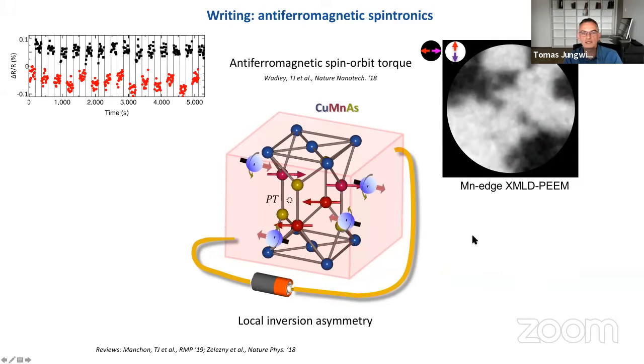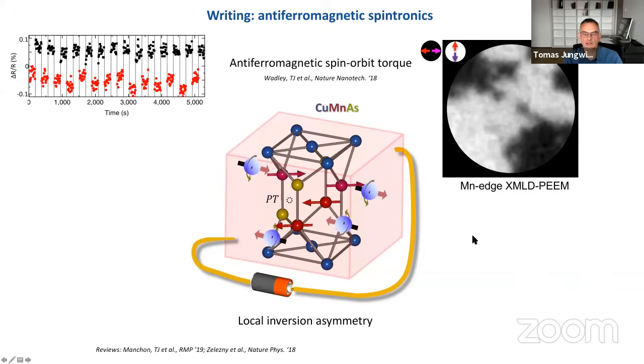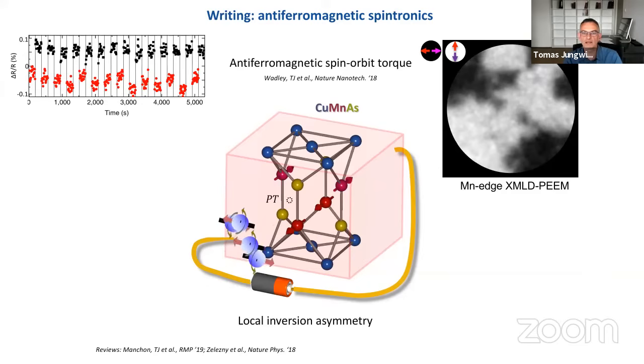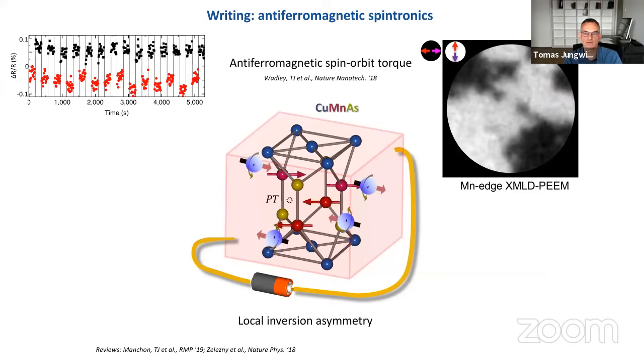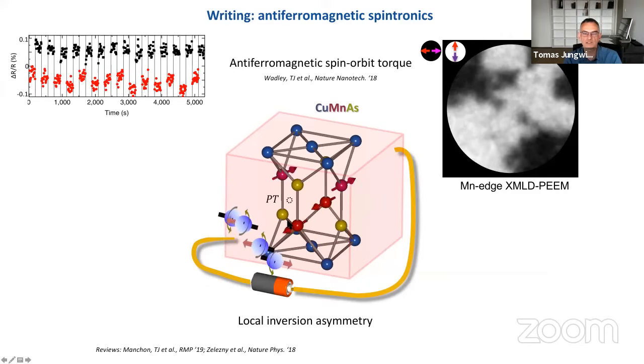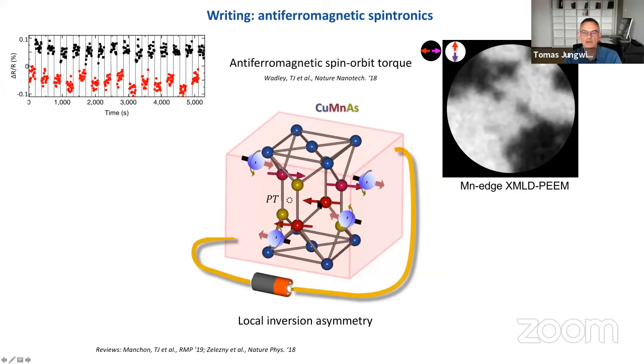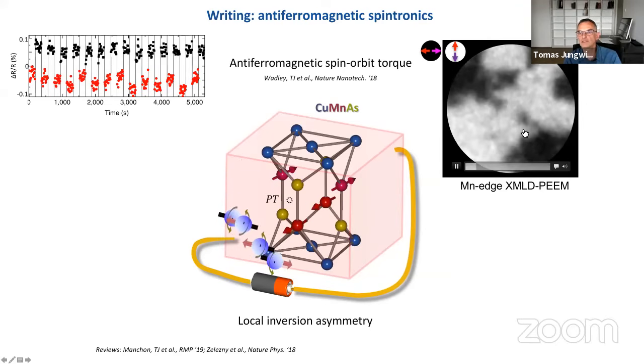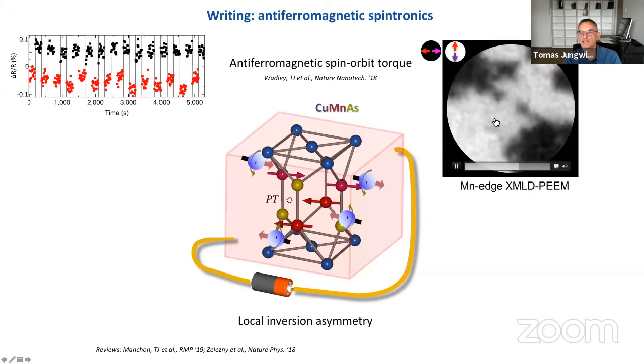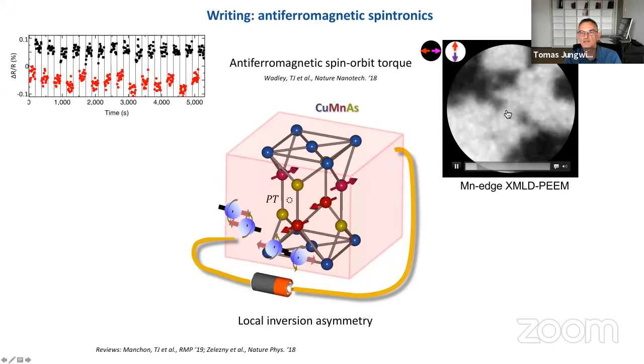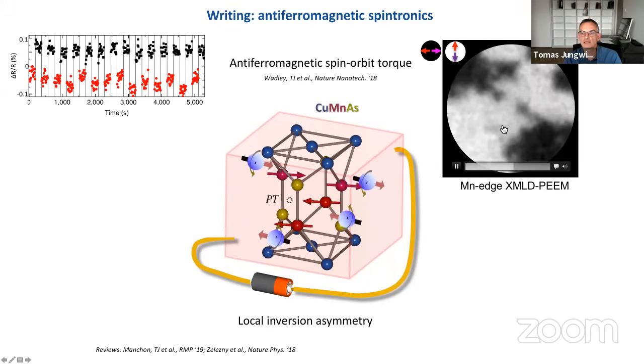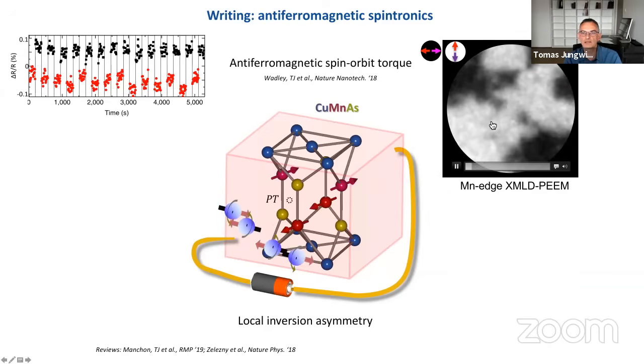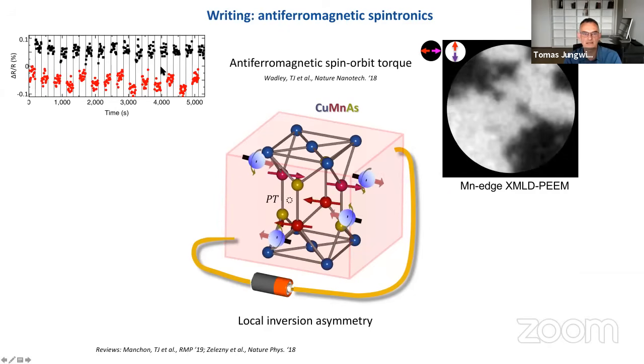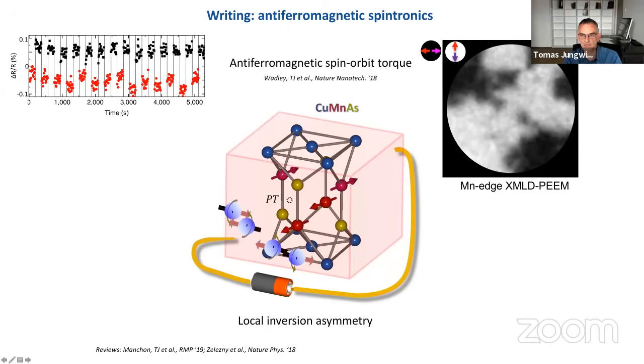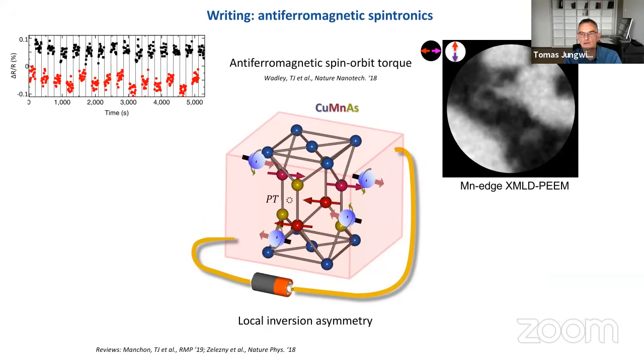So I'm showing again the images that I showed already before in the chapter on readout, but now I'm combining writing and readout. So because of this spin orbit torque switching, we're able to reorient large macroscopic domains in copper manganese arsenide by 90 degrees, image it by this X-ray magnetic linear dichroism, or also detected electrically by an anisotropic magnetoresistance.